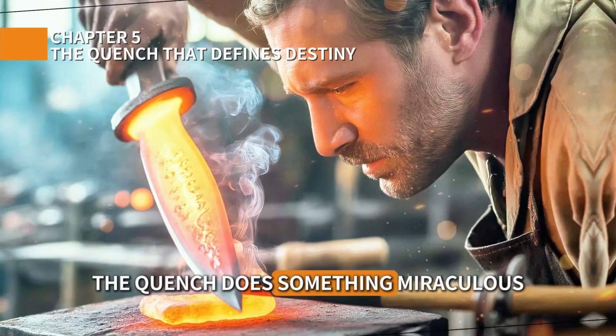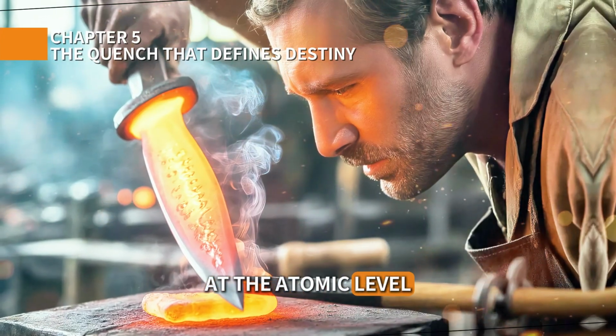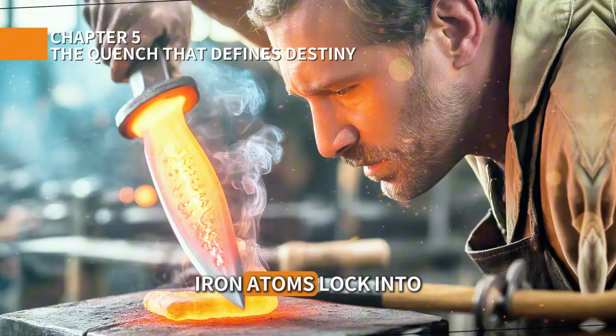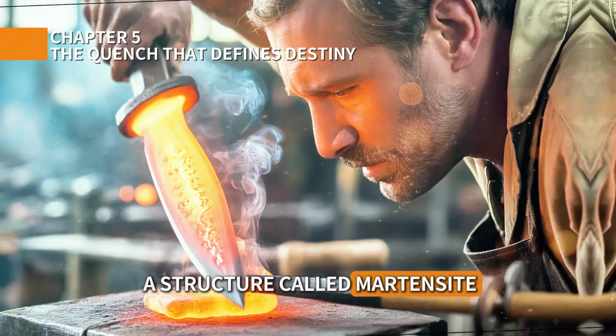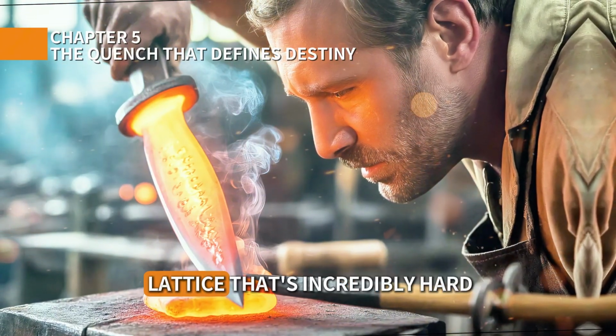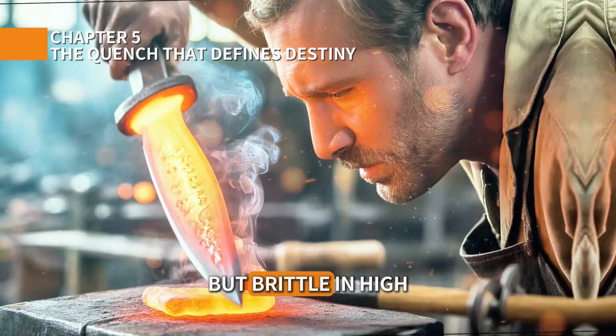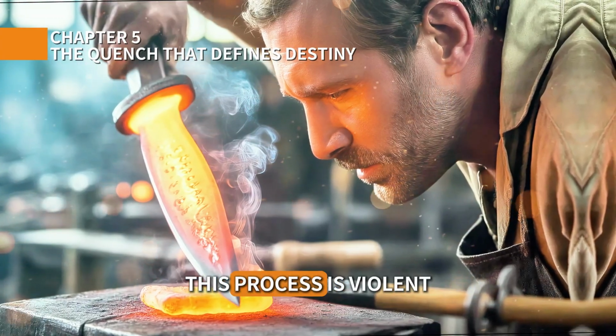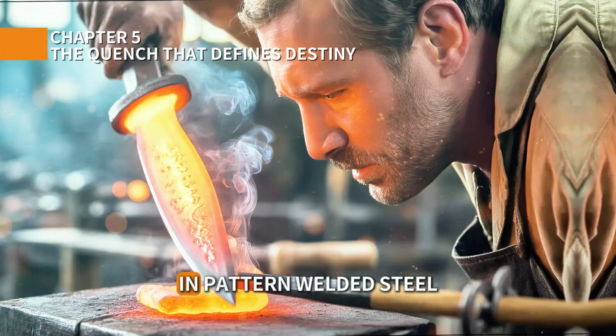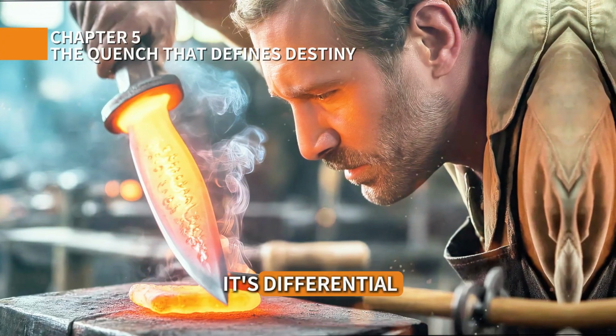The quench does something miraculous at the atomic level. As the blade cools, iron atoms lock into a structure called martensite, a needle-like crystal lattice that's incredibly hard but brittle. In high-carbon steel, this process is violent and uniform. In pattern-welded steel, it's differential.